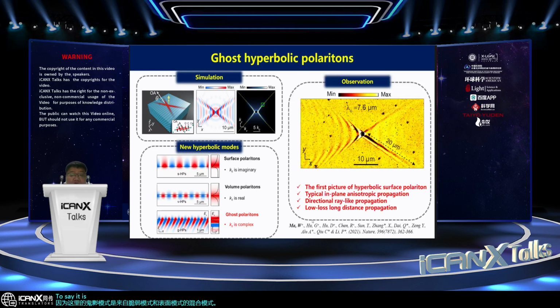To see it in real space by SNOM, we fabricate a metal antenna to launch the ghost polaritons along the calcite surface. We find some impressive features of this polariton. It shows confined and directional ray-like propagation at the right part of the picture. The linewidth of the polariton rays is only 2 micrometers, which is much smaller than the incident wavelength. And the propagation distance is up to 20 micrometers, maybe a record distance for all in-plane hyperbolic polaritons at room temperature. It shows the low-loss nature of the polariton in calcite.